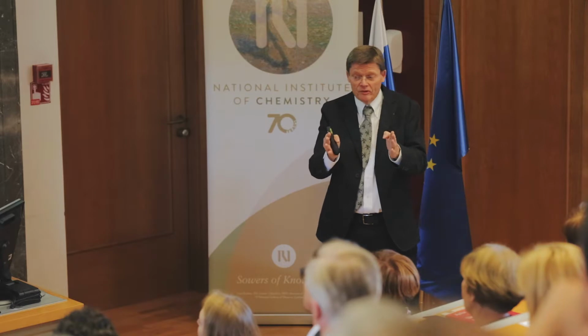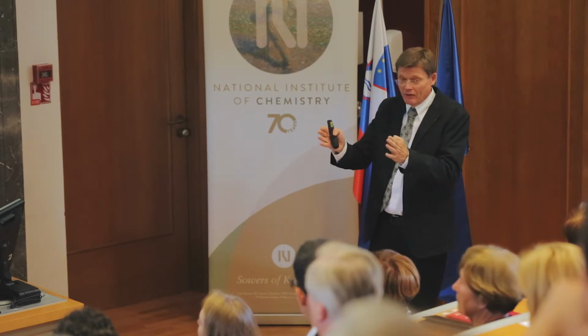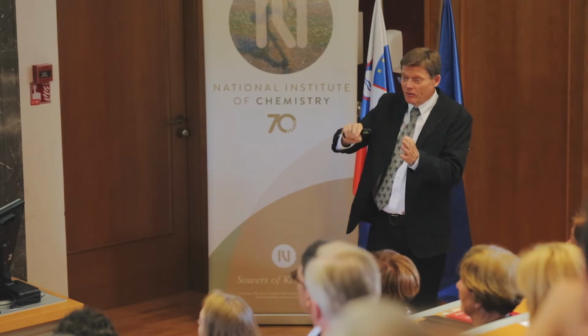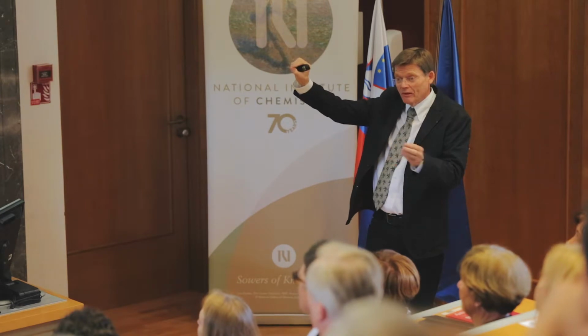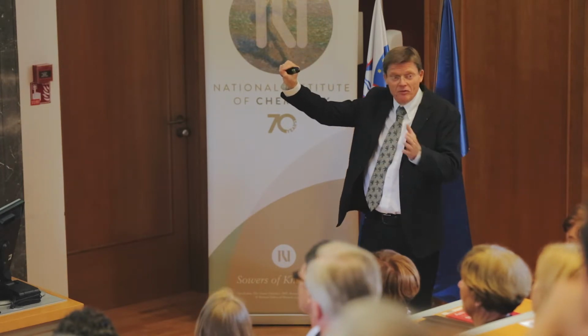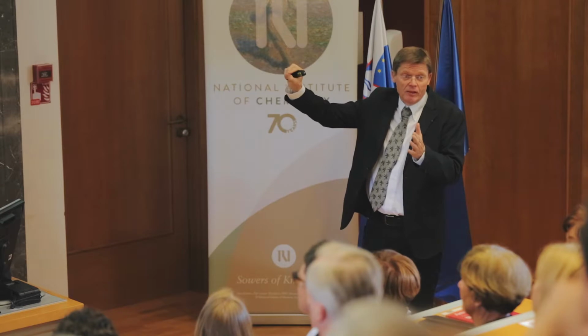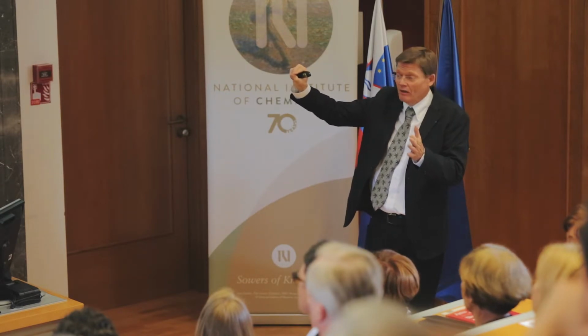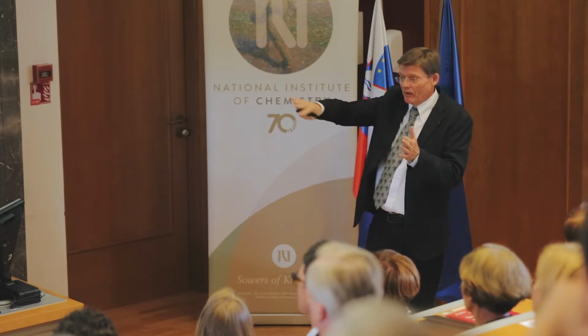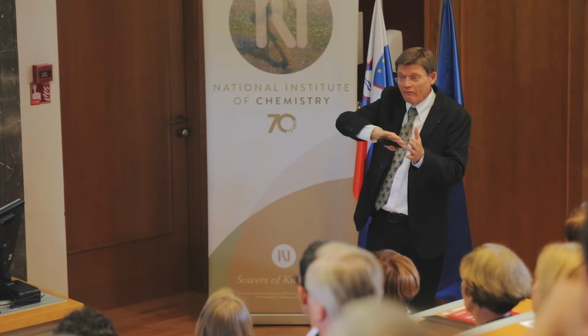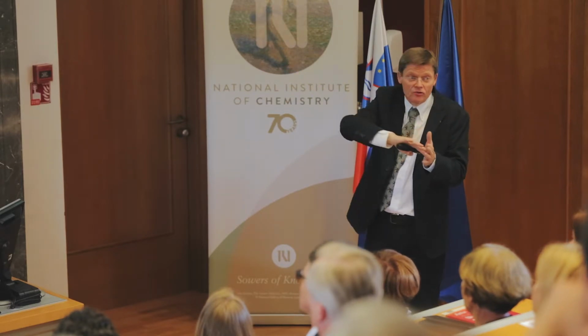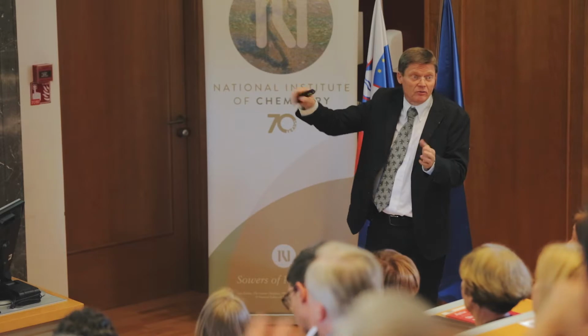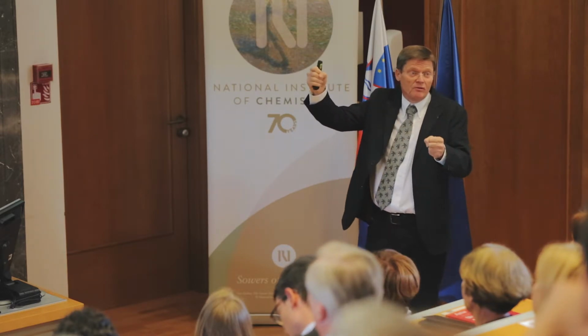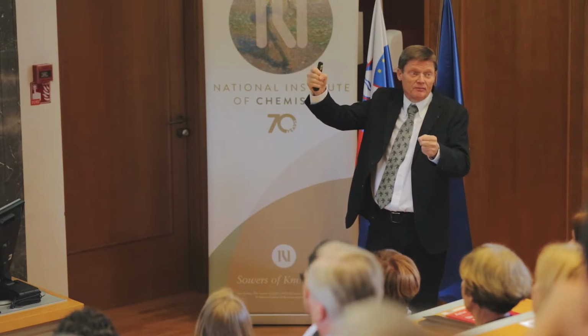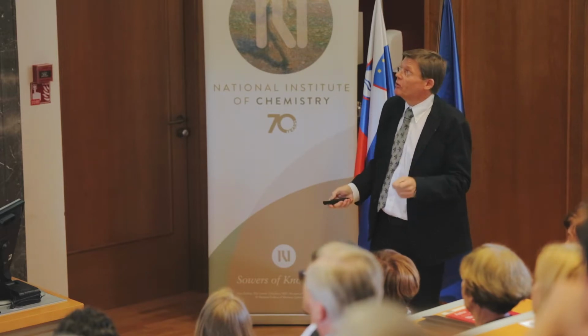The consequence is the electrons can go through, the ions cannot. So the ions will try to pile up on one side, and they will be depleted on the other side. This is happening in the bulk, where there is no charging. Everything is compensated by electronic carriers inside. So what you have is a variation of the stoichiometry inside. So you get really a gradient of your composition inside. That is a general response of a mixed conductor.